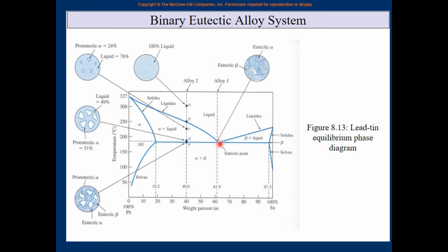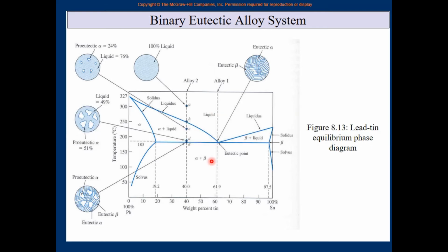This point is very strange. You see, just shift this dashed line to exactly this point. Here it is liquid, liquid, liquid. No liquid plus solid happens. It suddenly changes to complete solid, right? So this is the unique point. It was not there in any of the previous diagrams. We had the copper-nickel diagram, we had the silver-lead diagram, and silver-palladium. Liquid always becomes liquid plus solid and then becomes solid. Here, at one point, liquid directly changes into two solids.